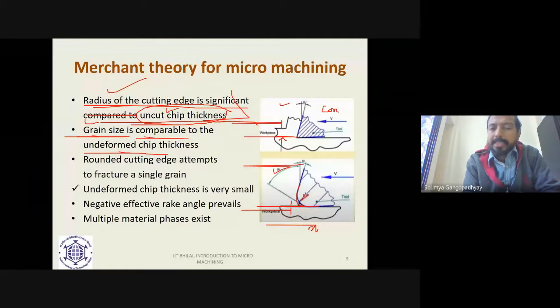The grain size is in the range of 1 micron, 2 micron, 5 micron, 10 micron, like that. Grain size. What is the undeformed chip thickness? Again, 1 micron, 2 micron, 3 micron, etc. What is the cutting edge radius? In the same order of magnitude. So three things are of the same order of magnitude: grain size, edge radius, uncut chip thickness.